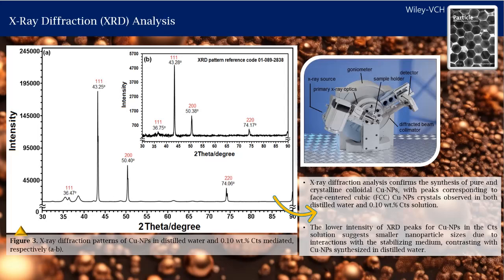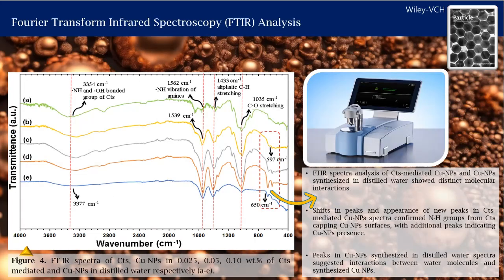X-ray diffraction analysis confirmed synthesis of pure and crystalline colloidal copper nanoparticles. Peaks correspond to face-centered cubic (FCC) copper nanoparticles crystals in distilled water and 0.10% chitosan solution. Lower intensity of XRD peaks in chitosan solution indicates smaller nanoparticle sizes due to interactions with the stabilizing medium, contrasting